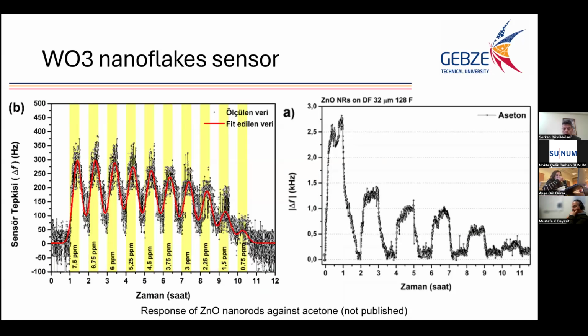Here you see the sensor response of the SAW against acetone. The concentration range is from 7.5 ppm to 750 ppb, so it's in the range of concentrations that exist in human breath. The data looks a bit noisy, but that is due to the insufficient precision of the measurement tool. We now have much better tools in our laboratory, but as I said, this noise comes not from the sensor itself, but from the measurement tool.